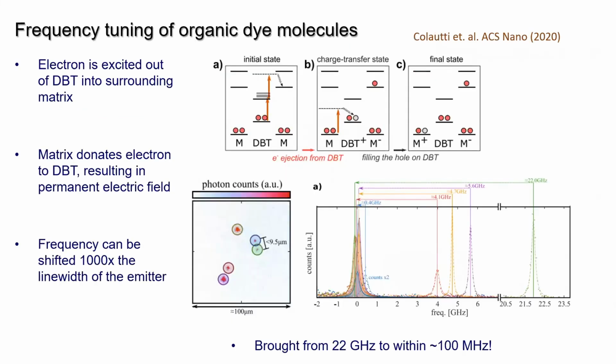and that's the fact that if you shine intense enough laser light onto a dibenzoterrylene molecule, it will shift the resonant frequency, and it will stay shifted after you turn the laser light off, for hours to days. This is very strange, right? Not really something we see in other quantum emitters. For some reason, it's not fully understood, if you shine an intense laser light, you'll bend the frequency, and you turn the laser off and it stays bent for a long period of time.